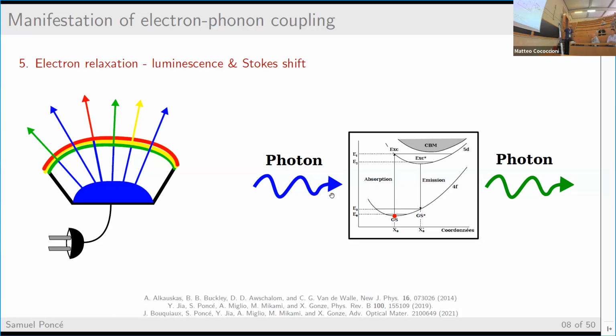Typically, for this one uses delta SCF that we saw yesterday, because for this, you see, it's some dispersion, this is a 5d state. It's actually quite localized. So the way this phosphor works is that you're doping the material with a rare earth, typically europium or cerium. And so what you're doing is a 4f to 5d transition of this dopant. And so those are localized in the band gap. And so you're trying to compute the Stokes shift of that localized object. And there it's easier to use delta SCF. So you're constraining the equation, relaxing, and then you can compute the Stokes shift and things like that.